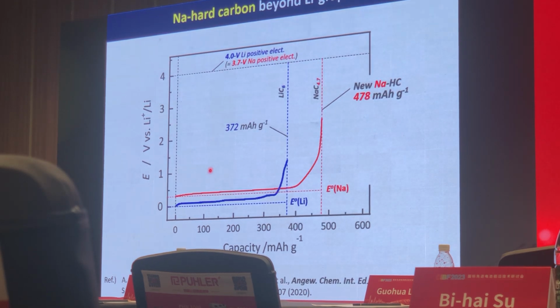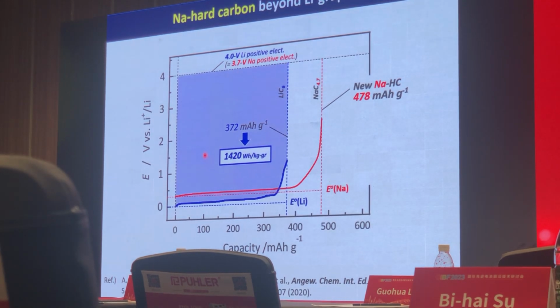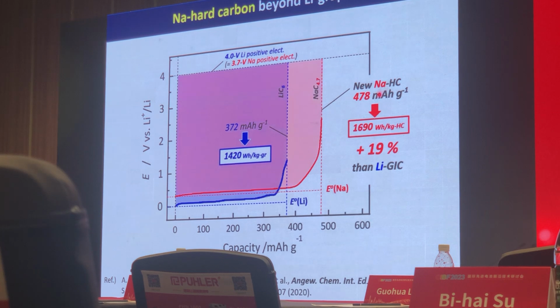So to compare the energy density, we assume that 4 volt lithium positive electrode corresponds to 3.7 volt in a sodium cell. In the case of lithium GIC, we can achieve an energy density of this area, corresponding to 1,420 watt-hours per kilogram. But by replacing it with sodium hard carbon showing high capacity, and by assuming the same positive electrode potential limit and capacity, we achieve almost 20% energy density gain over the lithium GIC cell.